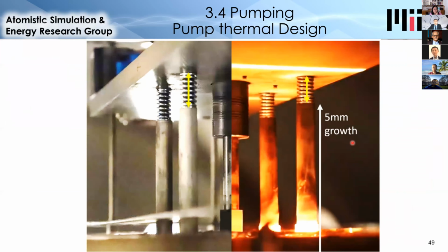This figure shows what happens when the pump system is heated up and why the springs I mentioned are so important. So on the left is the system when it's cold. The springs are not compressed very much. And on the right, the springs are compressed almost completely because of the axial expansion of the ceramic and the graphite beneath it. You can see the color here is the heated pump system radiating light because it's so hot. This exposed surface that's white at the bottom here, it's only about 1200 degrees Celsius. The pump is much hotter, but about a foot lower in the insulation.